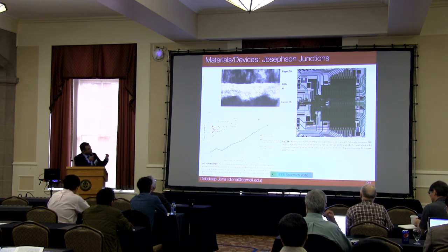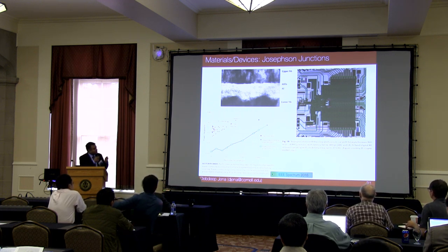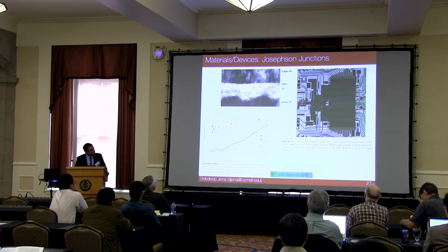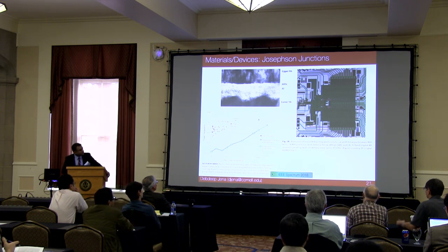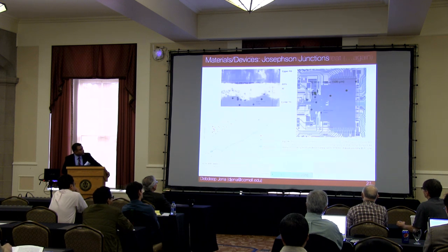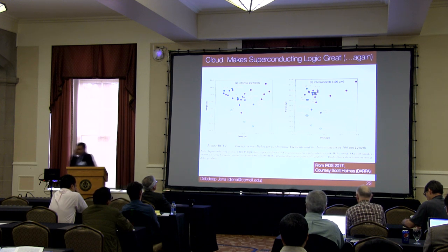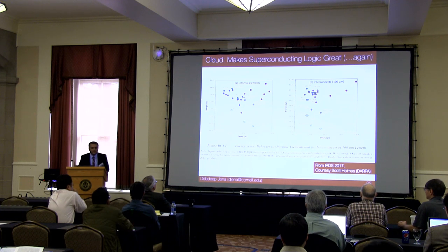And the coherence is tied a lot to material science. Here's an example of a new kind of Josephson junction. These are made out of two-dimensional materials, layered superconductors. This is niobium selenide stacked on top of another niobium selenide, and you start seeing Josephson junction-like behavior. Here's one from the group at Lincoln Labs. They're using graphene and boron nitride as their tunnel junctions for the Josephson junction. Similar thing, but different new kinds of Josephson junction.